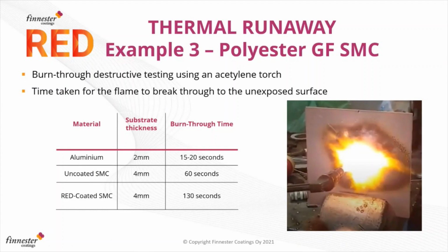And one final example from the thermal runaway work that we've been doing in battery casings. There are some people who are using acetylene torches. So there you really are talking high temperatures and very aggressive fire parameters. And in this case, it's looking at how long it takes for that torch to actually burn through the substrate to the rear side, to the unexposed side.